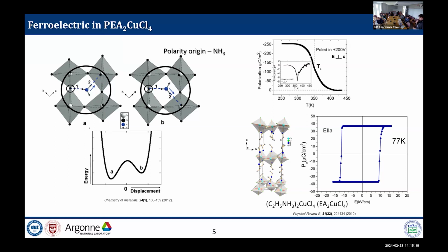But the amount of polarization is too small because the polarity origin is only this NH3, so they can't measure it that way. The electric hysteresis looks like this: external electric field versus polarization plot. The EA2 copper tetrachloride is similar to the PEA2 copper tetrachloride. They have a linker, just CH2, CH2, and NH3, and the origin is similar. Here, they could measure the electric hysteresis loop at 77 Kelvin. So similarly, this is the origin of the ferroelectricity in the PEA-based quasi two-dimensional organic-inorganic hybrid system.